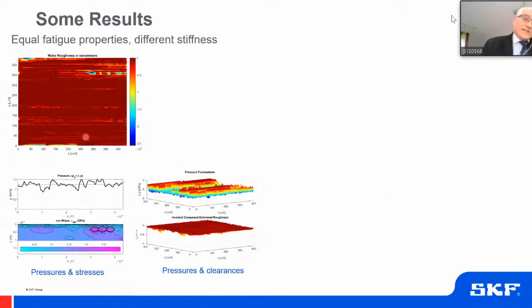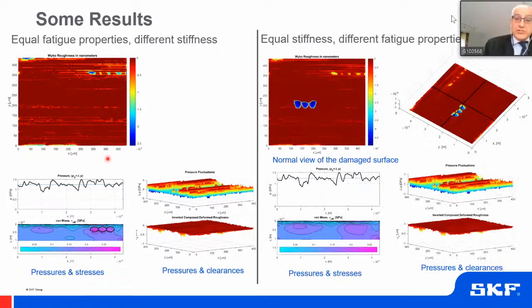So you can see that this is a lubricated problem. So you can see the hydrodynamic pressures here. You can also see the inclusions and how they concentrate the stress because they are stiffer than the matrix. But for this particular case, you see the clearances and the pressures. For this particular case, we did not generate a failure. Now, the same condition, but now we introduce equal stiffness, so you will not see this stress concentration because the stiffness is the same. You can see here.